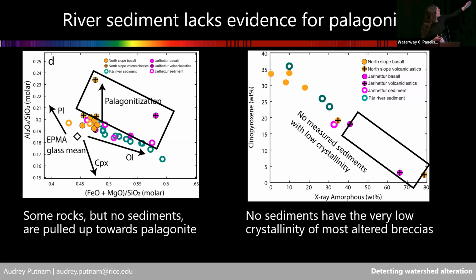So on the left, I'm showing aluminum over silica and then mafics over silica for all of our samples. Broadly, we can see there's the distribution between more felsic and more mafic components of our system. But we know from our EPMA data that palagonite, that hydrothermal alteration phase, pulls up towards higher aluminum over silica. And we can see that we have two watershed rocks, some of those really amorphous 70, 80 weight % X-ray amorphous rocks, getting pulled up by the hydrothermal alteration, but we don't see that expressed in any of our sediment samples. We can also see from the bulk XRD on the right that we don't see any of these river sediment samples showing those really amorphous compositions. And we are not capturing that space of the watershed lithologies with these.